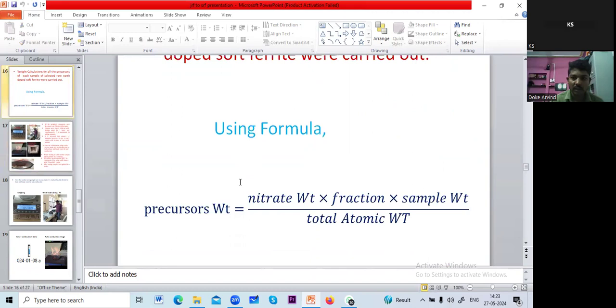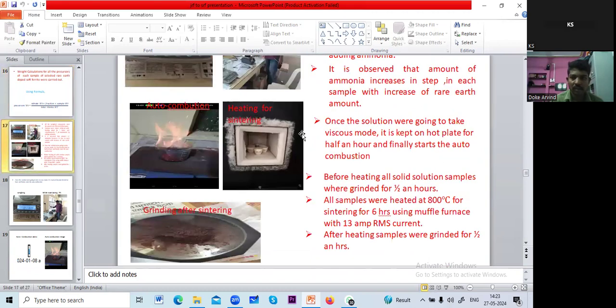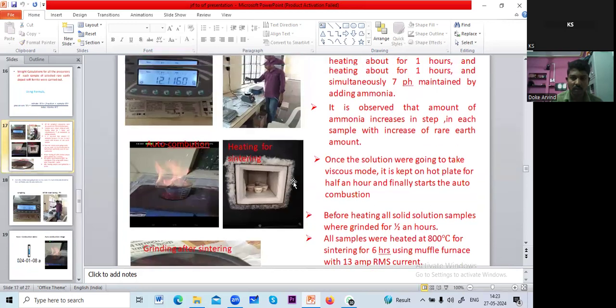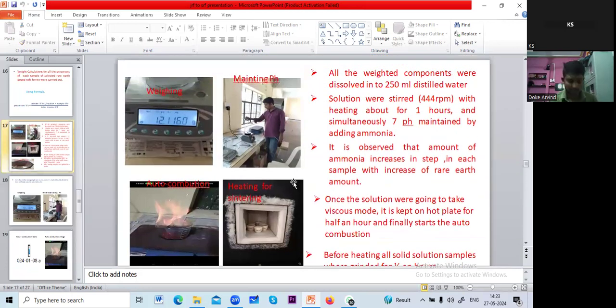In this slide, the synthesis method is mentioned that was used during the synthesis of my sample. All weighed compounds were dissolved in 250 ml distilled water, and the solution was stirred at 444 RPM with heating for about 1 hour, simultaneously maintaining pH 7 by adding ammonia.